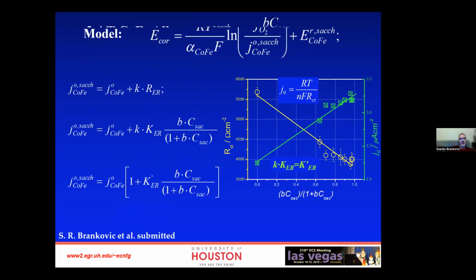All right, so let's put this in the map. This is our general model that I showed you from the corrosion literature. And what we want to say is that it looks like from our experiments that our exchange current density for corrosion of anodic dissolution of the cobalt iron can be expressed as a linear function of the electroreduction rate of the additives.